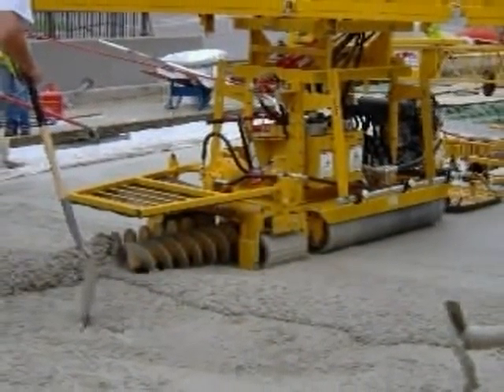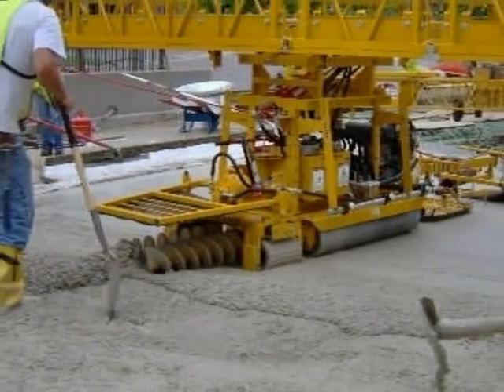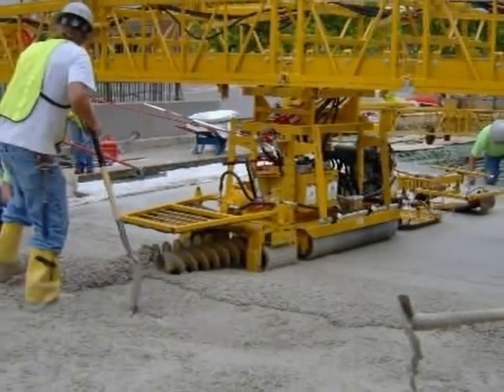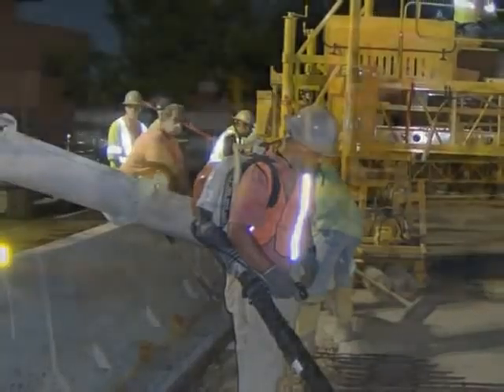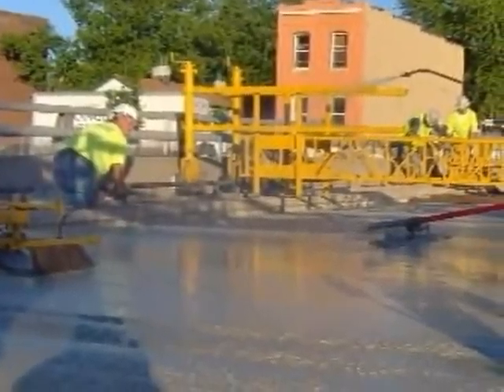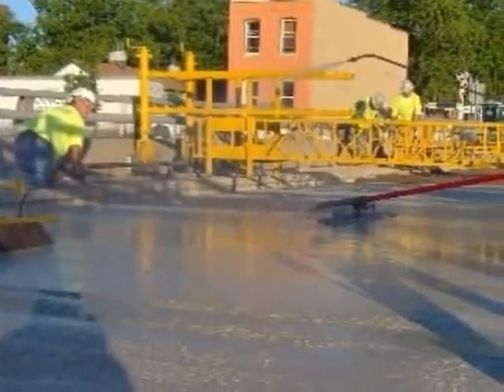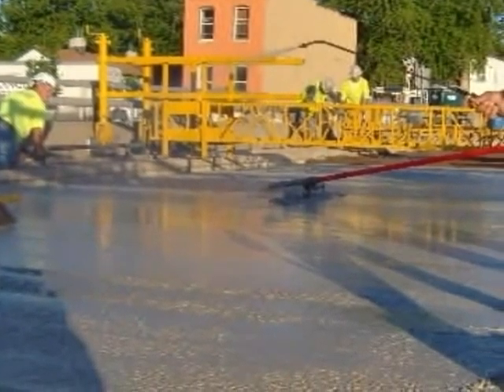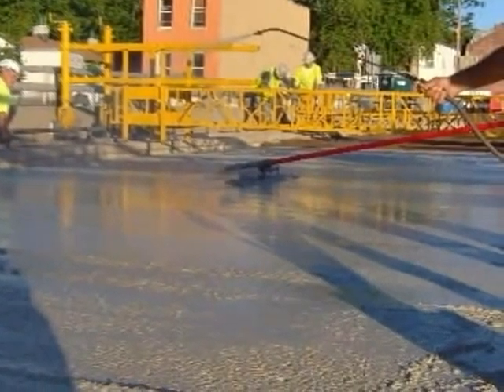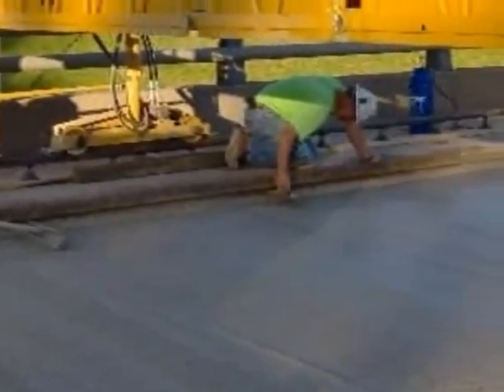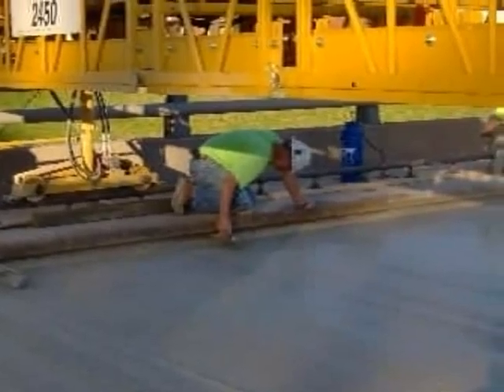Rapid-set low-cement concrete was produced at the traditional 658 pounds of cement per cubic yard, as with other wearing surface concretes. Based on the overperformance of this mix design, the cement content was reduced to 572 pounds of low-cement, with physical performance results still above that of competitive concrete materials.